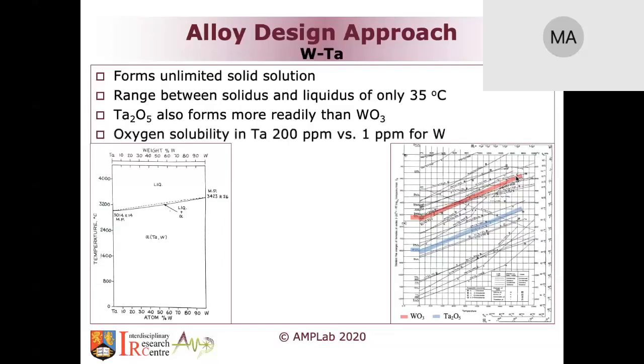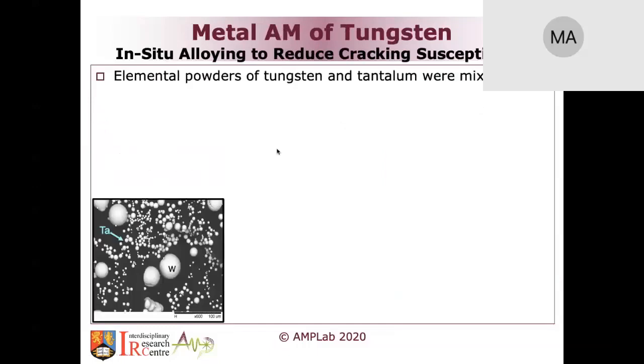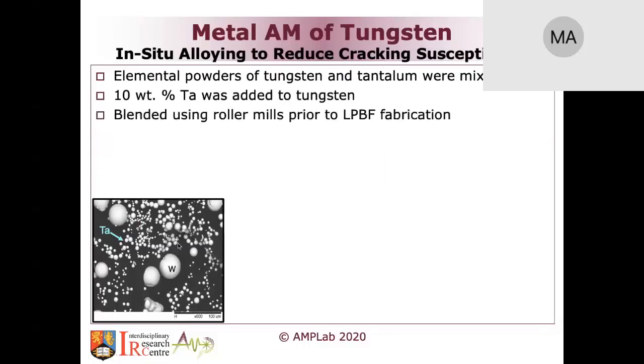So that's the point. Oxygen solubility in tantalum is around 200 parts per million, whereas it's 1 part per million for tungsten. So adding a bit of tantalum might help to reduce the cracks that we saw before. The way we did it in the initial investigation, we simply did in-situ alloying, whereby we had tungsten powders. We blended a lot of tantalum into it, about 10 weight percent tantalum added to tungsten, blended before LPBF fabrication.